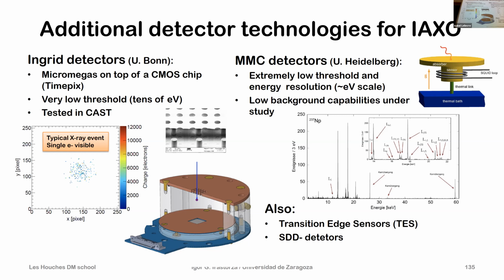On your previous slide with the IAXO collaboration trying to get very low backgrounds, why would they choose lead shielding? Isn't that not very radiopure? Aren't you going to have a lot of radioactivity from the lead shielding itself? No, if the lead is pure enough, it's not radioactive. The only problem is lead-210, an isotope that is produced with the lead, and it's radioactive. Sometimes underground experiments use archaeological lead, because the lead-210 has decayed, with about 20 years of decay.